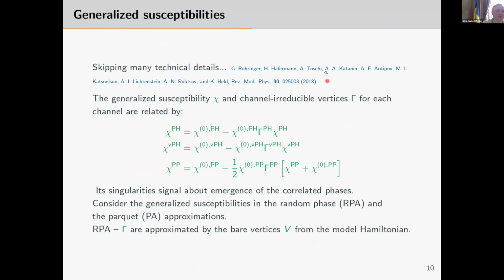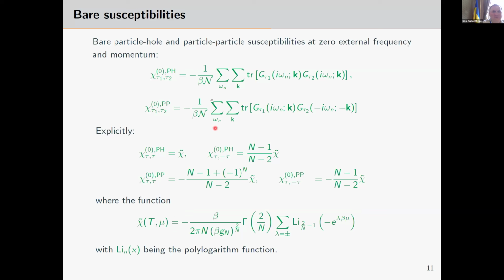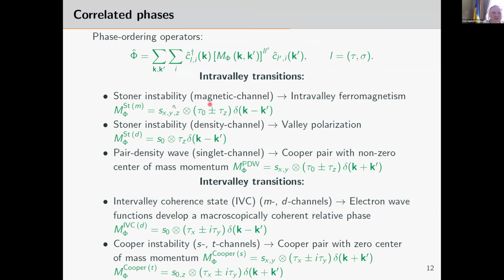I skip in my talk a huge amount of technical details and just state that we calculated the generalized susceptibility and channel irreducible vertices for each channel, and the singularity of this susceptibility is a signal of instability. Exactly like in superconductivity, the susceptibility diverges. In our work, we did both. This just shows that the bare susceptibility can be calculated analytically. Another one shows instability: this is a magnetic instability, Stoner instability, and superconducting instabilities.